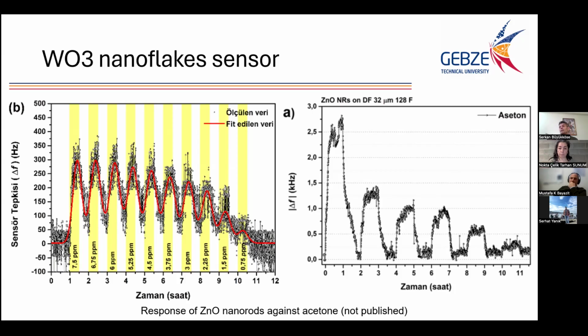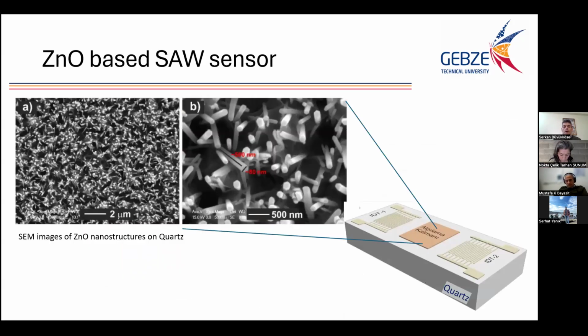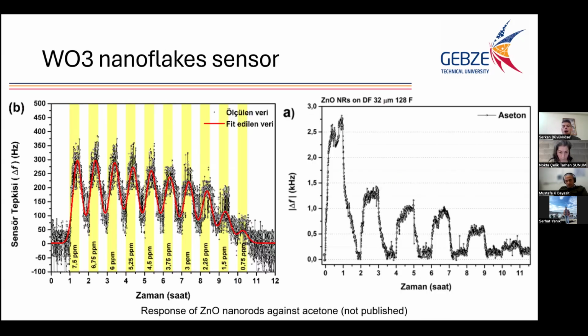Its precision is 7 ppm. It means that for the 1 megahertz frequency, it gives 7 hertz of precision. Did you think about it in the way of 2 probe or 4 probe, because your transducers are with 2 probes, right? Yes, the general classic type is 2 probes. Maybe you can think about the 4 probe technique while printing or in the microfabrication lithography process. Because when you use the 4 probe, the self-resistance of the system can be eliminated, removed. You know it as a physicist. So maybe you can think about it for your further work or study.